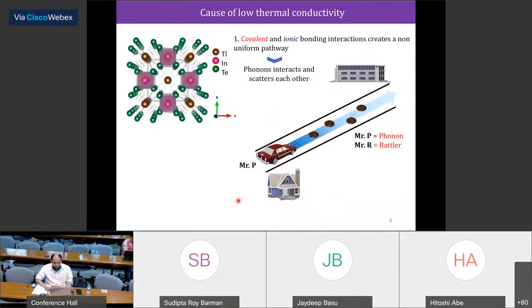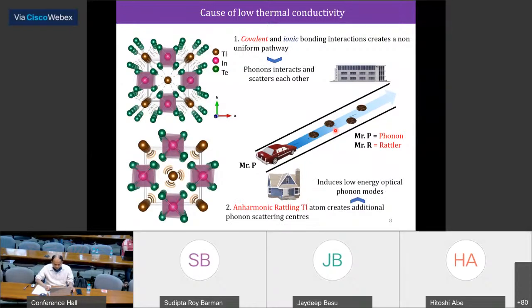So in the first case, as I told you, we have potholes in the road. That means the bonding hierarchy makes the phonon scatter moderately, but once we have rattling atoms, we can think we have another car on the road, doing like this, and that's why this car delays too much. Mr. P is delayed too much for the office, and when he reaches the office, his condition is like this. So basically the phonon dies out heavily in the system, and that's why we have ultra-low thermal conductivity from the combined effect of bonding hierarchy as well as anharmonic rattling.